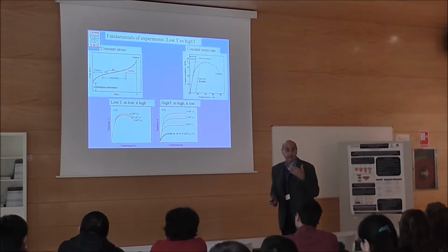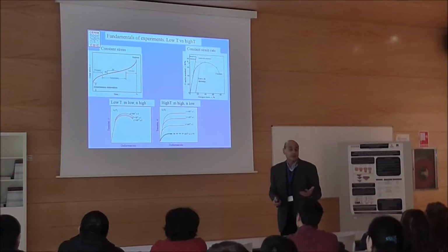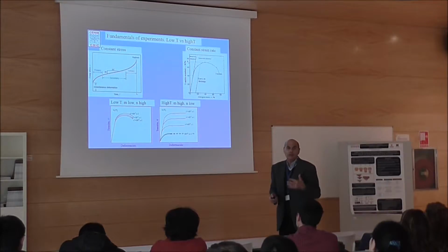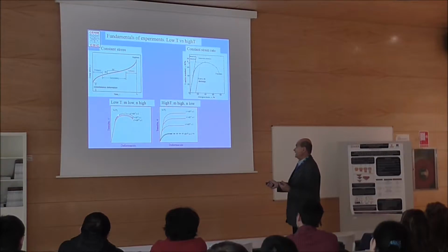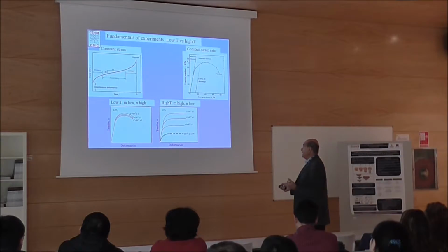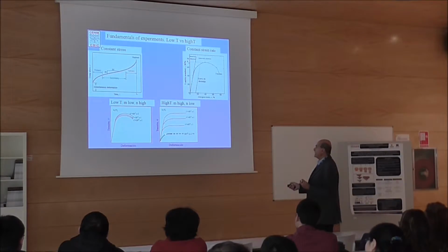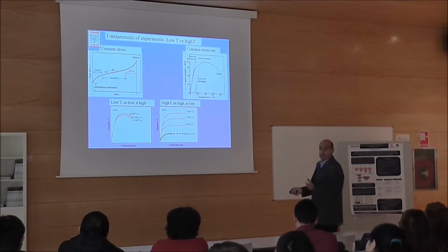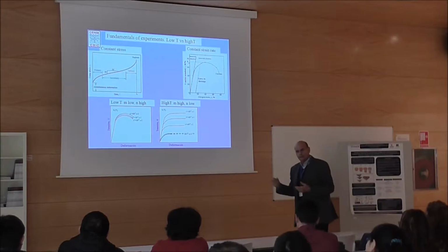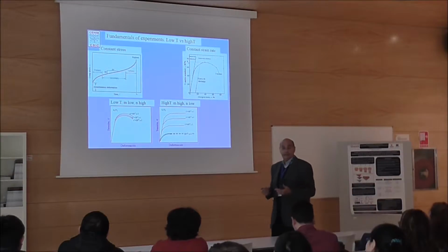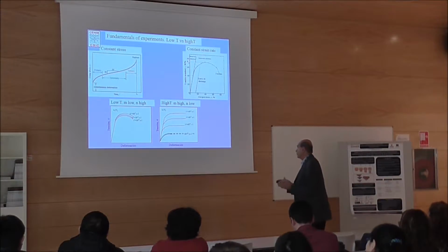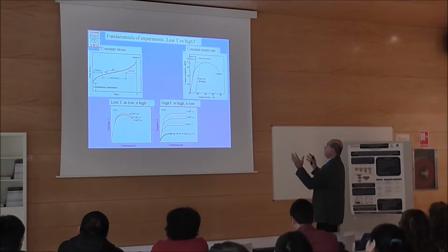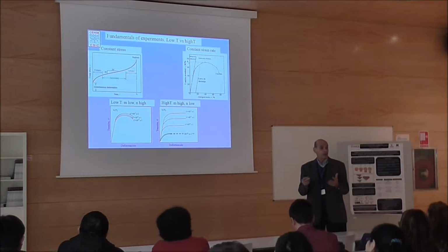That means that the strain rate sensitivity is very low. So we do not have a big sensitivity to changes in the strain rate. In contrast, at high T, we have a strong variation. If we change the strain rates, we have a variation that gives us values of the stress exponent, as we will see later, that are very low. So this is the basics of the experiments on creep.